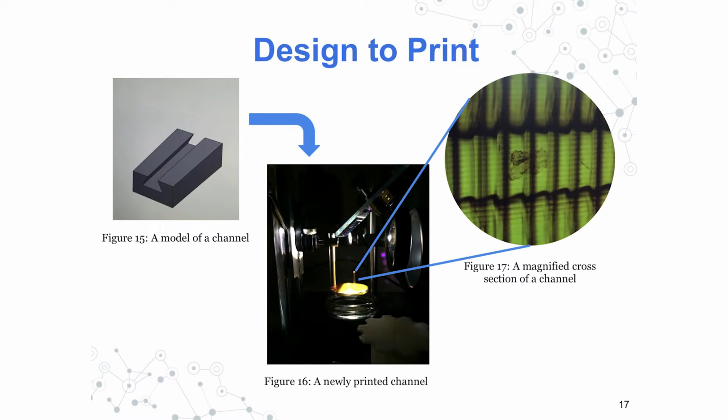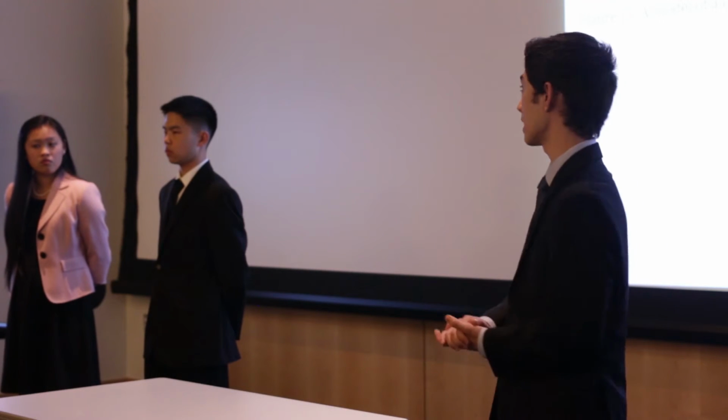So the second thing that we chose to pursue was creating movement in a small portion of soft robotics. First, we created a small channel with the help of CAD, or the computer-aided drafting program. This is just a short section of what we created, and it's essentially a rectangular prism with a small trapezoidal prism cut out of it. This is to induce capillary action once in contact with acetone. Capillary action would draw the acetone up one side of the channel, produce swelling via absorption in that one side, and thus produce flexing because of the uneven absorption of acetone.